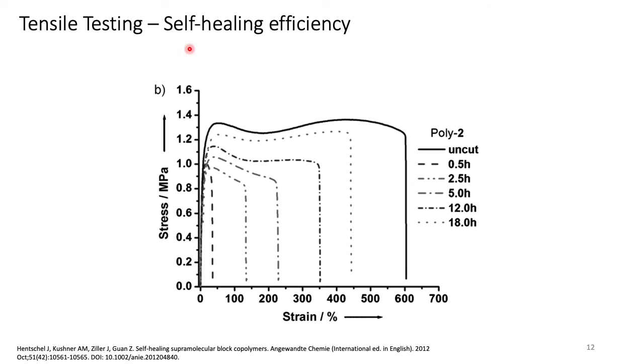So how can we determine the self-healing efficiency using tensile testing? We can do that by plotting a stress versus strain plot for the uncut material. That means we are stretching the material until it is cut apart, and then we compare this curve to the cut material. First we cut the material and then allow it to self-heal for a certain time, and after that we stretch the material using tensile testing, obtain the plot, and then compare the first plot to the second plot. So for example, in this experiment, after 18 hours of self-healing, they obtained a self-healing efficiency of around 90%.